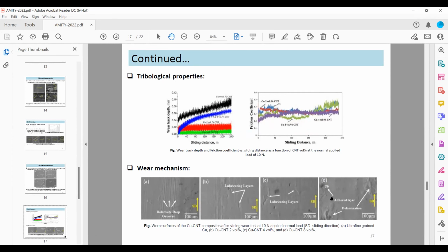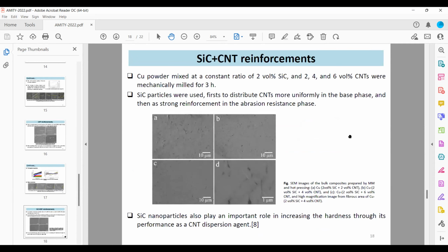But increasing the CNT also increases the agglomeration, and it can cause delamination wear and formation of cracks. So as CNT volume increases, it causes delamination and agglomeration. To minimize it, silicon carbide particles are used, because the almost spherical silicon carbide particles break up the agglomeration of the carbon nanotube clusters, and they create local shear stress and uniform distribution in the matrix.